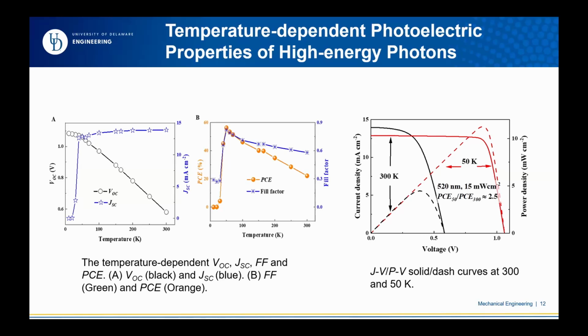So typically, the cell that we measure using a single laser is about 22%. Once we go down to 50 Kelvin, we get a 56% increase. No one has reported this before. That is the highest energy efficiency at that point. You can see here, as temperature decreases, efficiency increases, and then after that point it decreases again. So there is an optimal power generation at 50 Kelvin.